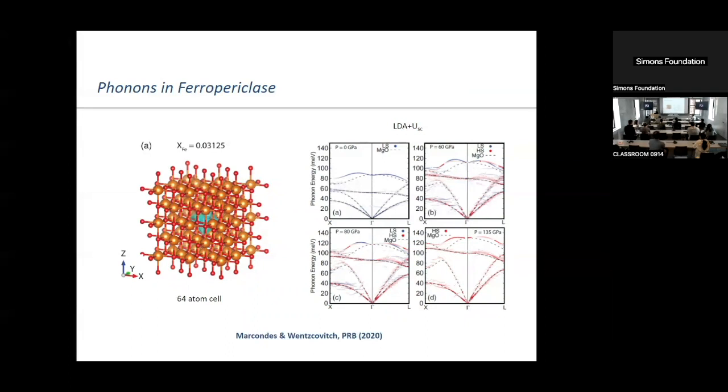And also conceptually, I mean, the answer may just be that it's dilute. Yes, exactly. The theory you presented previously was essentially the generalization to this richer situation of the usual binary alloy thing. Now, I might imagine that somewhere in this, I have a first order phase transition with phase separation. The binary alloy thing doesn't give me that. So where does phase separation come in around the first order transition? You may have that. If you are at x equal 0.5, you may separate. You may have phase separation. I see. But it's the small x's here. In two different ferropericlases with different composition. Yeah. Okay. Yeah.